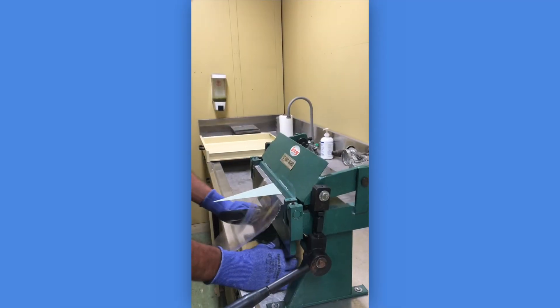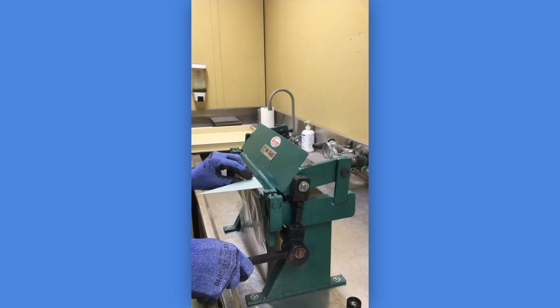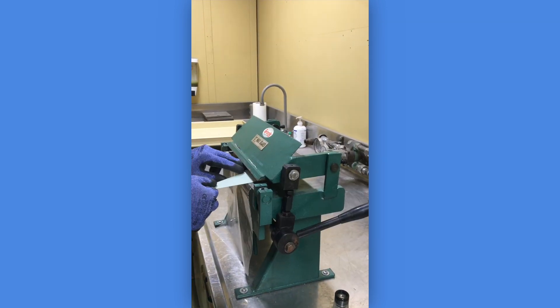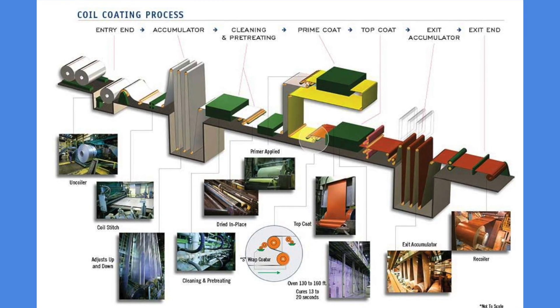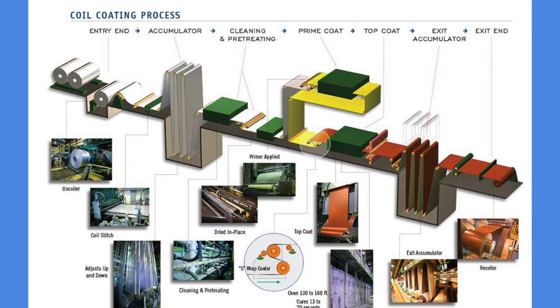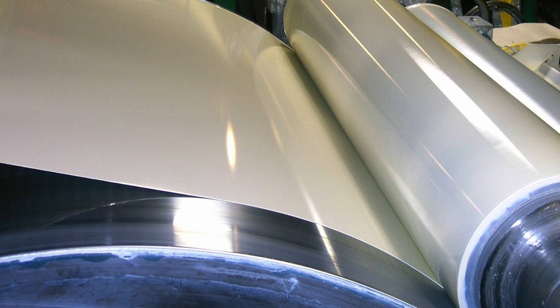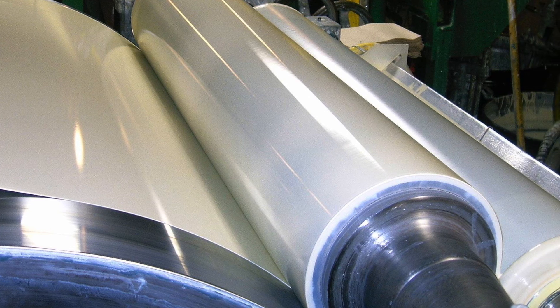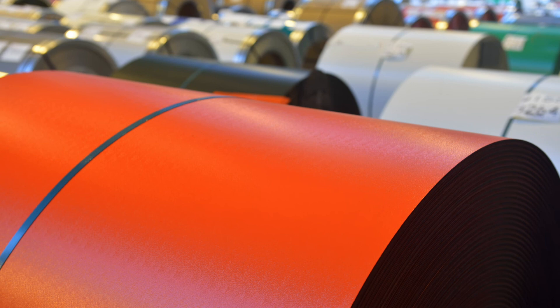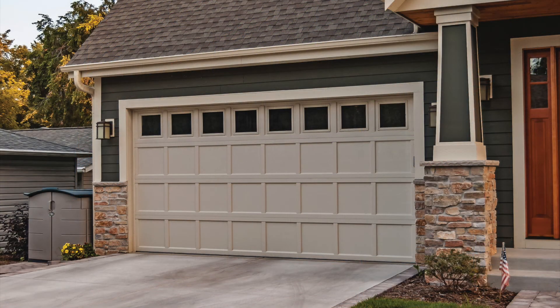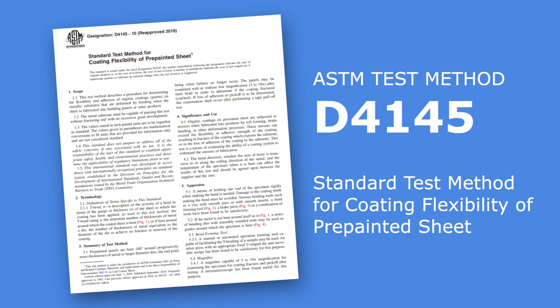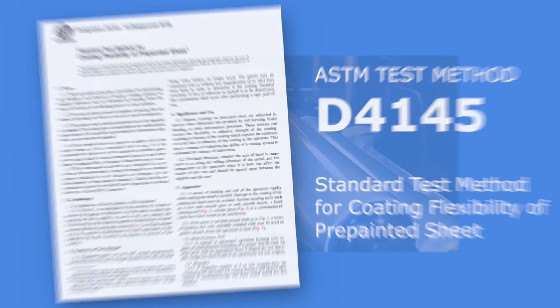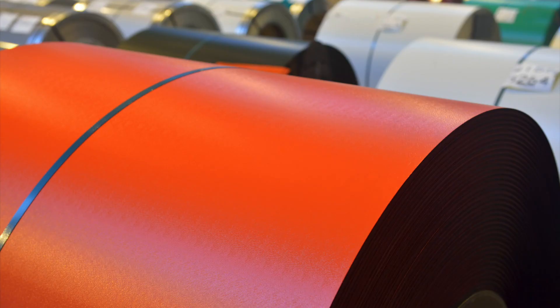Note the cracking and pick-off at each bend. One last iteration to the test method is to bend a triangle-shaped sample. This has the advantage of exposing each of the bends, which may be helpful for initial and future inspection, and serves as a permanent record. The advantage of the production of pre-painted metal is that a continuous web of flat metal is cleaned, pre-treated, and painted under highly controlled conditions. Coils of pre-painted metal must demonstrate suitable flexibility as the final part is fabricated. Metal building panels, garage doors, rain carrying accessories, refrigerators, HVAC units, and other products all undergo some degree of fabrication, and the T-Bend test is a critical test routinely performed on a coil coating line to assure that a proper level of cross-linking has been achieved and not exceeded.